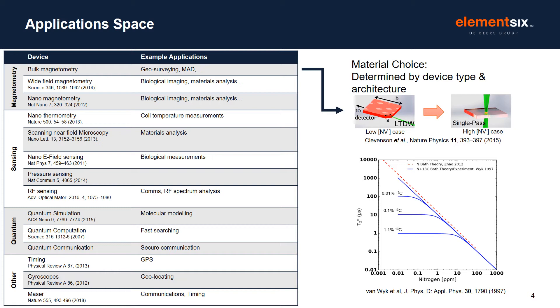However, we then need to find ways to illuminate all the NV defects in the diamond, along with applying uniform magnetic field and microwave pulses, which can introduce engineering challenges. One way to solve the illumination challenge, for example, is to use a light trapping diamond waveguide to bounce the light around. However, using this obviously introduces other challenges — for example, a small deviation of light injected caused by vibration will significantly change the light path. As such, single pass techniques may also be better for some applications and therefore will benefit from high nitrogen and NV content.